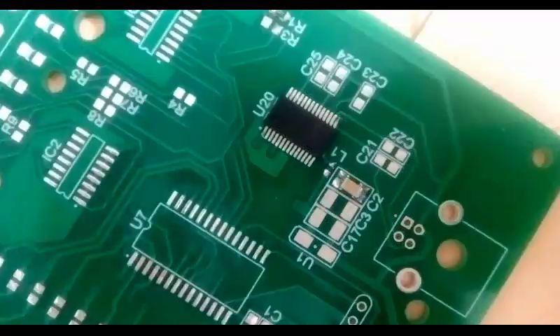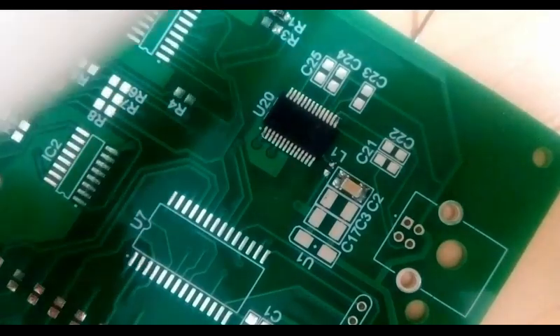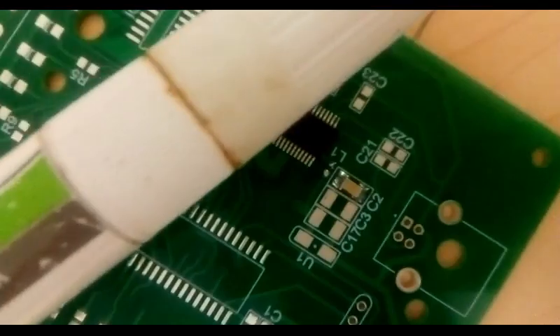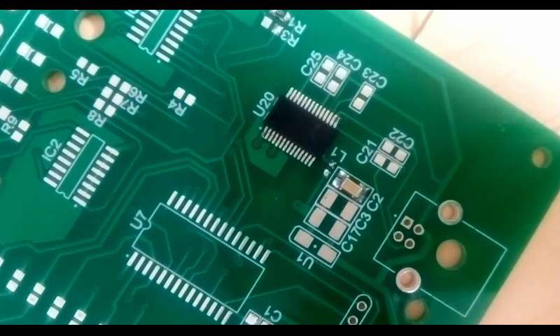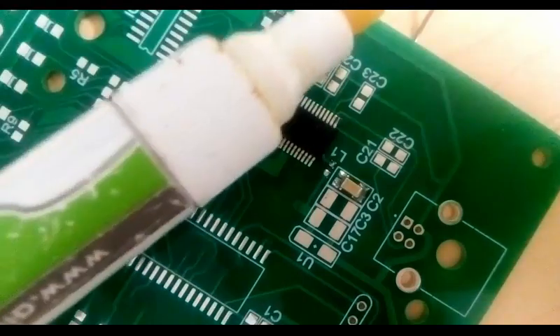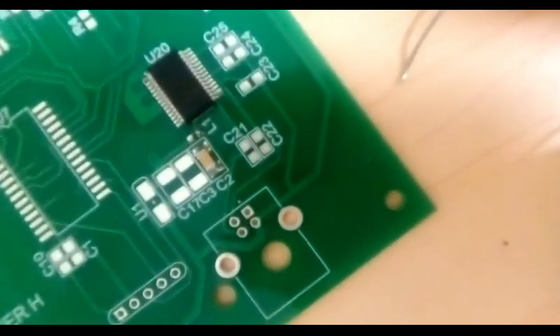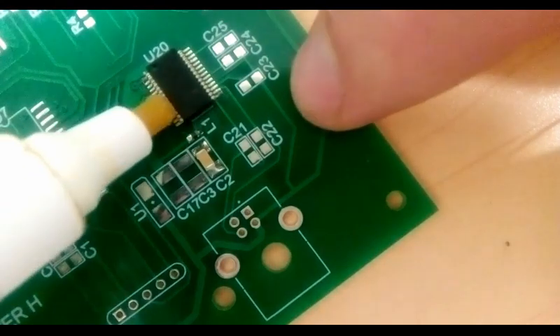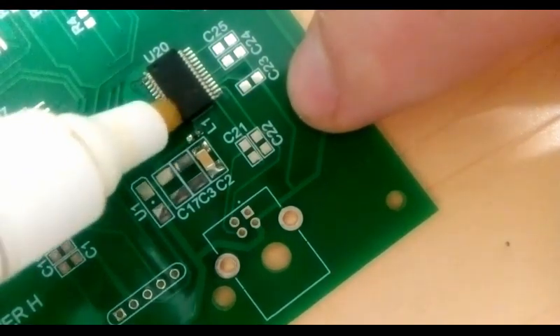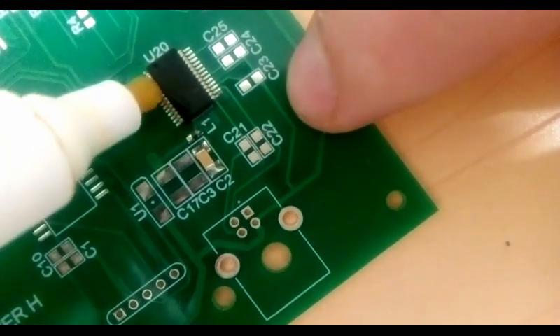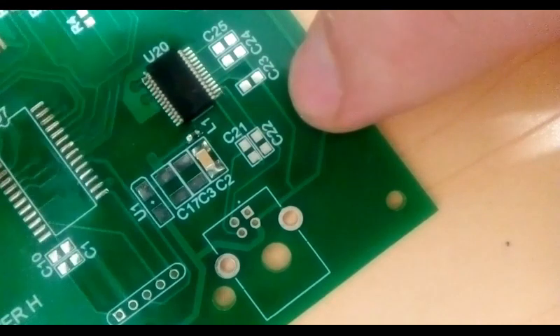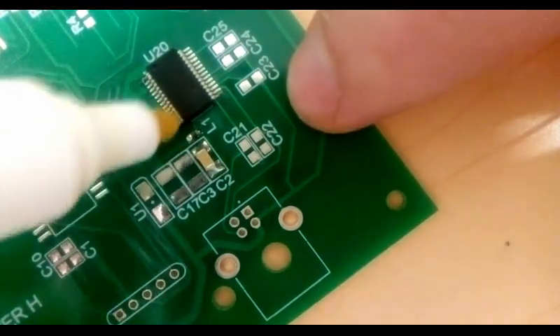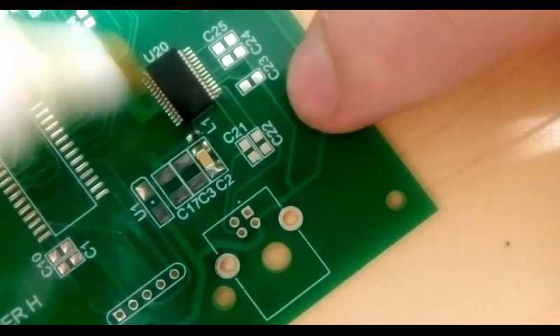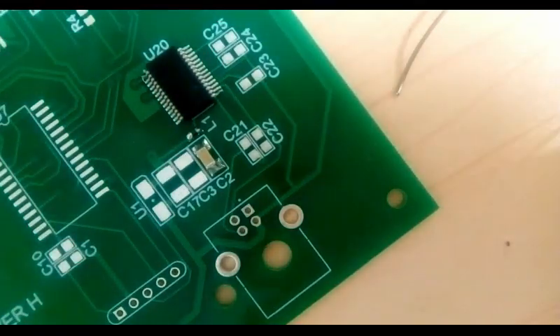Now we need the secret ingredient, flux. Flux pen. Now we need to shake the pen if we haven't used it for a while. Don't be stingy with the quantity of flux. Push in the nib and let it flow. You can see it's wet on the chip and there's a good quantity of flux on the pins. Now this will evaporate with the soldering iron and make some nasty noxious vapors, so don't breathe them in.